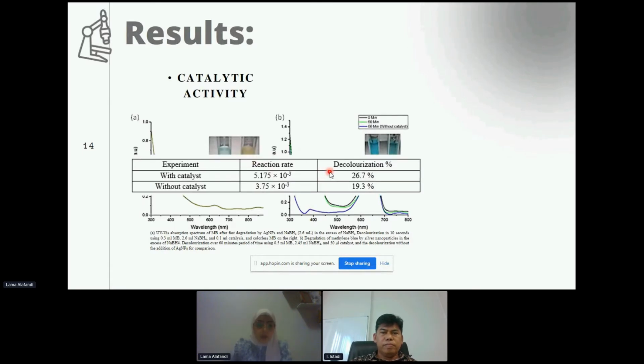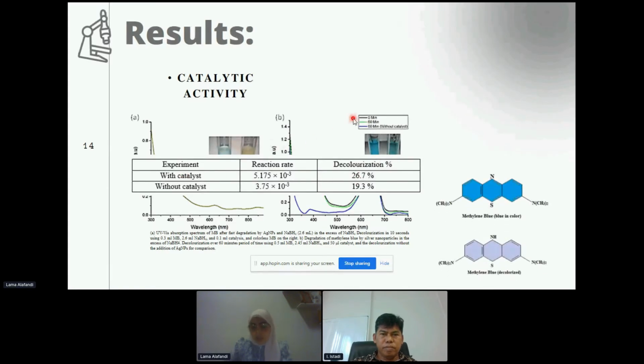For the calculation, the reaction rate we see with catalyst is higher, and the decolorization percentage is higher with a catalyst. This reaction is called the electron relay effect, where silver nanoparticles work as a donor of electrons for methylene blue, and the electrons accepted by methylene blue will activate the methylene blue to be a redox catalyst and turn the color to a more colorless color.